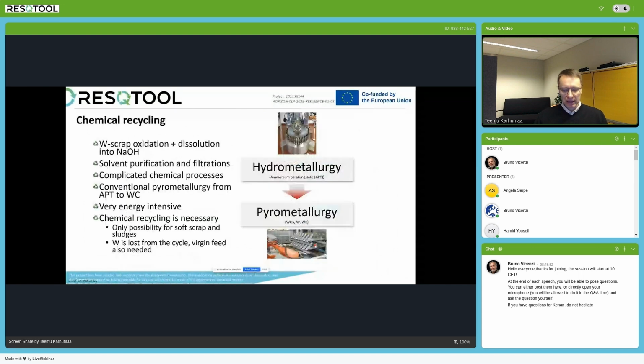Then the full chemical recycling method, which is normally utilized, or which owns the majority of the market share in the hard metal recycling market. The tungsten carbide and cobalt and other elements are oxidized and dissolved into sodium hydroxide, and then there are complicated steps of solvent purification and filtrations, and then ammonium paratungstate is the outcome from the hydrometallurgical processes. This is then calcined to tungsten oxide. Then tungsten oxide is reduced to tungsten powder, and this is then carburized to tungsten carbide powder.